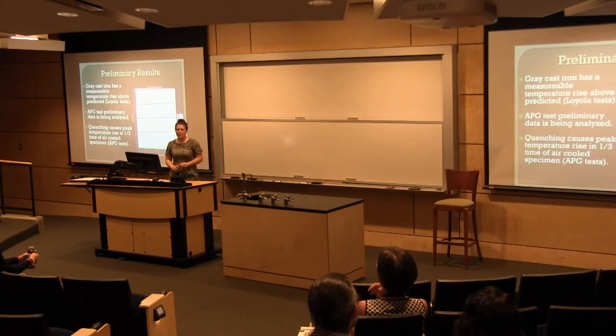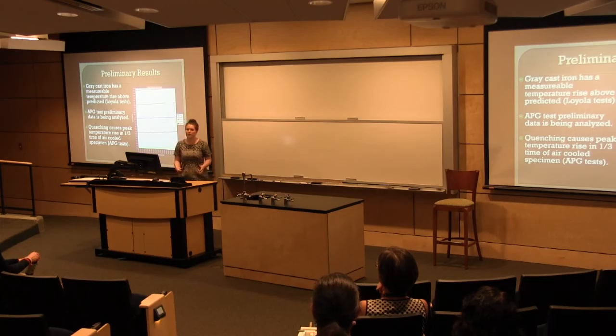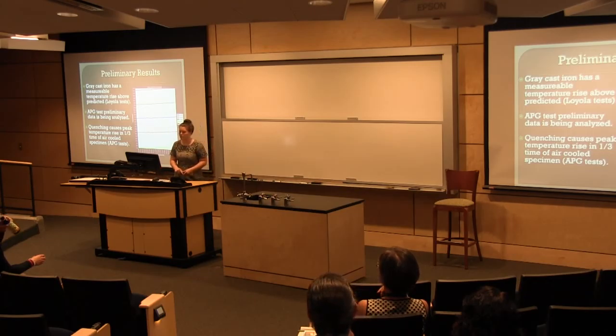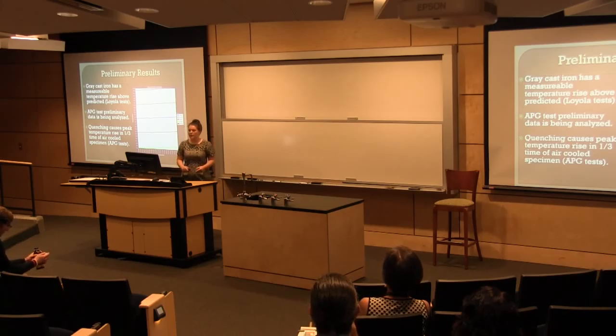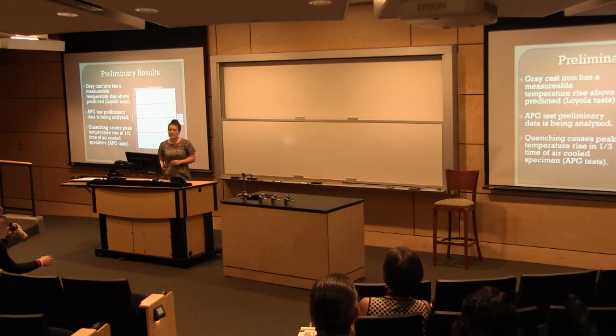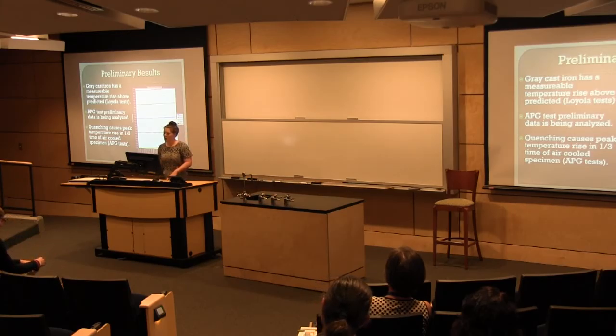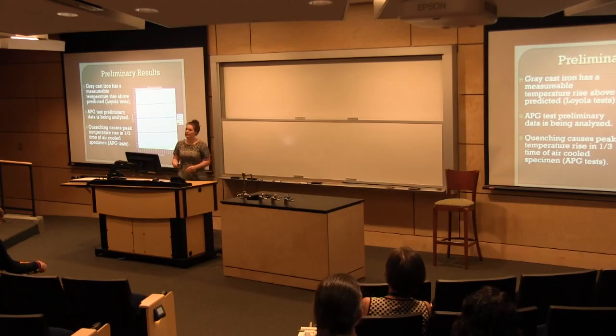In terms of preliminary results, gray cast iron has a measurable temperature rise above the predicted. And again, the predicted was 3 degrees from Dr. Bailey's modeling. And then I showed you the 15-degree rise in temperature, which is what this point is talking about. And then the Aberdeen Proving Ground test data is still being analyzed. This is actually a graph that is outputted from their software. But the main thing we can see here is that to see the same rise in temperature between a quenched and non-quenched cast iron bar, it's taking about a third less time for the same temperature rise to happen in a quenched bar versus a non-quenched bar.